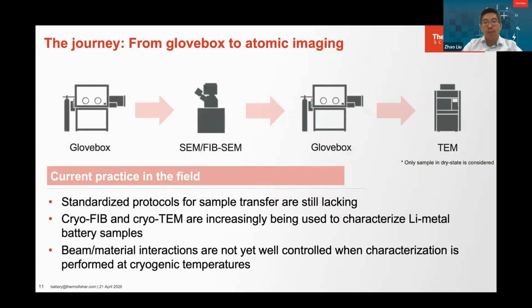To address those challenges, let's first look at the sample journey from the glove box all the way to atomic imaging inside the electron microscope. The sample starts in the glove box on the left, then moves to the SEM and the dual beam FIB-SEM to do the imaging or lamella preparation. Then you move back to the glove box, exchange to a different transfer holder, and then insert it into the TEM to do the final atomic characterization.